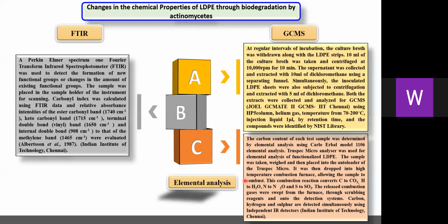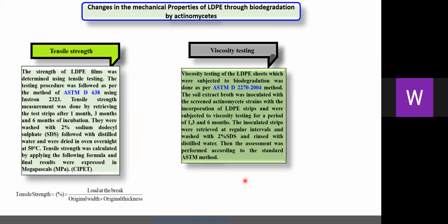Changes in the mechanical properties of LDPE by actinomycetes were assessed by tensile strength and viscosity testing. The tensile strength of the LDPE film was determined using tensile testing. The procedure followed the method of ASTM D638 using Instron. The tensile strength was calculated by applying the following formula and the final results were expressed in megapascals, MPa, CIPET Chennai. Viscosity testing of LDPE sheets subjected to biodegradation was done as per the ASTM method. LDPE strips were subjected to viscosity testing for a period of 1, 3 and 6 months and assessed by the standard protocol.